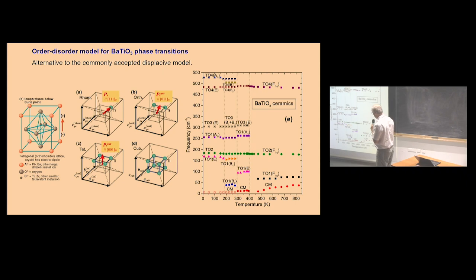The lowest frequency phonon slightly changes, but not too much. But below the phonon is another excitation. We call it central mode, and this is responsible for most of the dielectric anomaly in barium titanate.